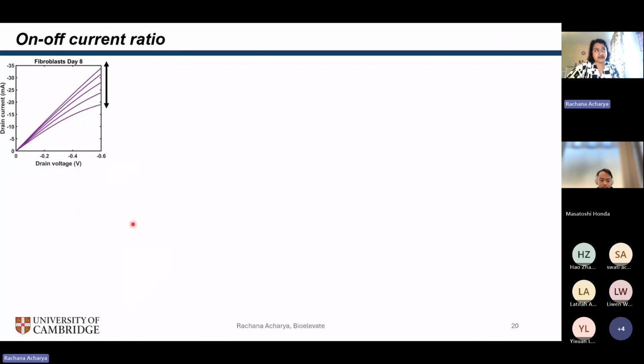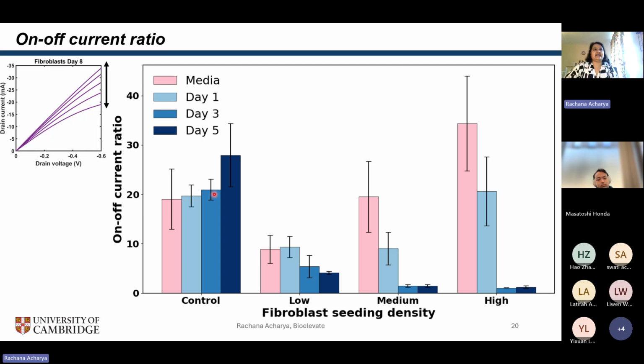Starting with our first figure of merit, the on-off current ratio. Here, the pink is my media control, just before I seed the cells on my scaffold, and then as the colors get darker, I have day 1, day 3, and day 5. What you can notice is that for the control, I actually have an increase in the on-off current ratio, but it's mostly consistent across devices. Whereas for the devices with cells, for the low density cells, we can see a slight decrease in the on-off current ratio, which means that this switching off was impacted a little bit.